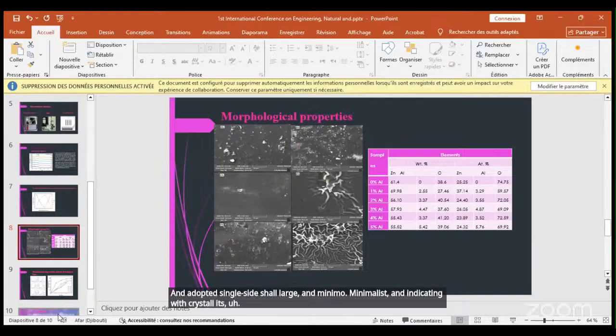This figure represents the morphological properties. The SEM analysis of zinc oxide thin films doped with varying concentrations from 0 to 5% reveals a strong correlation between surface morphology and crystalline size. Undoped zinc oxide shows large agglomerates and minimal strain, indicating well crystallized grains. As aluminum doping increased to 3%, crystallite size decreases and strain increases, indicating lattice distortion from dopant incorporation.